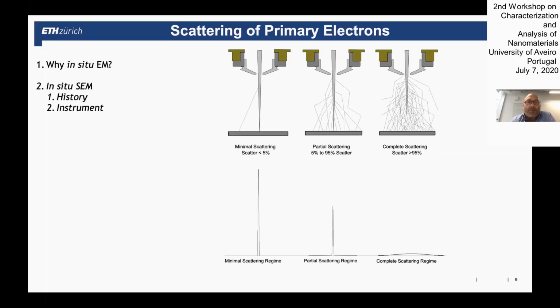And what happens, of course, when there's gas inside is that the electrons can get scattered on the gas molecules, and then you get actually a distribution of scattered electrons. And the more gas you have in your chamber, the more of the primary electrons get scattered, and only a small fraction of your initial beam really still hits the place of focus. But the good news is that all the scattered electrons get really randomly scattered to random positions, and they basically only contribute to a background.